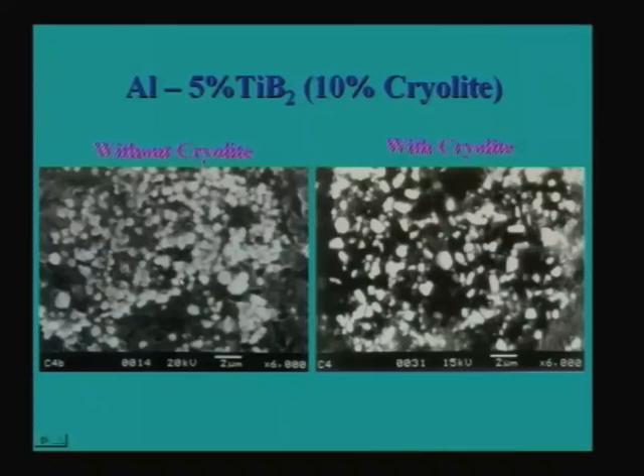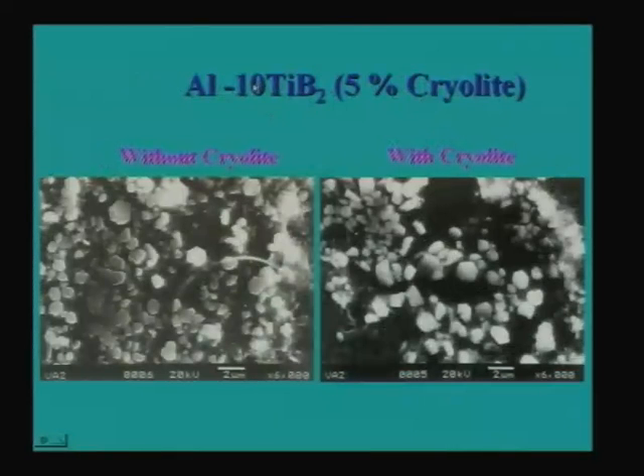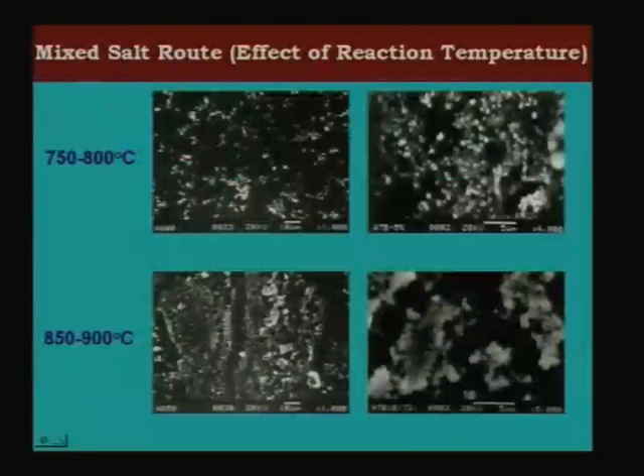These particles which you form have also some Al3Ti. If you do EDAX on individual particles, you will also find some Al3Ti in them. Similarly, one can also do it for 10% TiB2. In case of 10% TiB2 also one can get a similar nature.